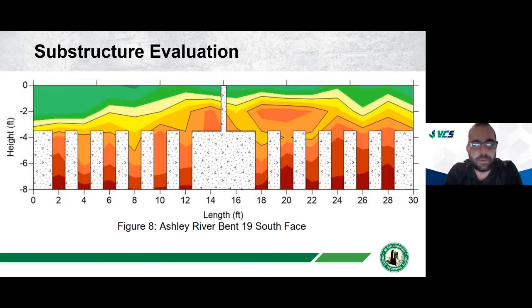And again, doing the corrosion potential survey on those substructure elements, you can kind of see, this is the structure that was lower, closer to the water. And you can see there's a lot of active corrosion up into the cap. The piles are obviously actively corroding, and so we see a lot of those hot colors there. And so this is where the corrosion is quite active throughout the structure.